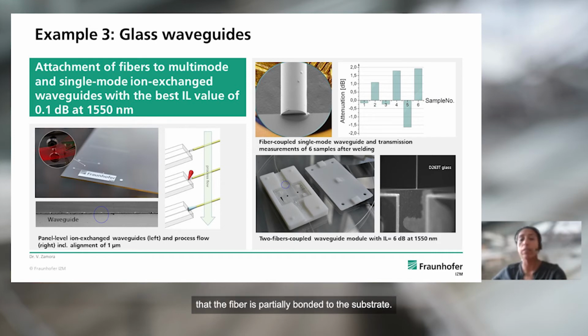Except that the fiber is partially bonded to the substrate. The reason is related to the location of the waveguides, which is very close to the surface. Despite this small difficulty, a series of 6 single-mode fibers were attached to the 6 inputs of the single-mode waveguides. The best insertion loss value was found to be 0.1 decibels at a wavelength of 1550 nanometers.